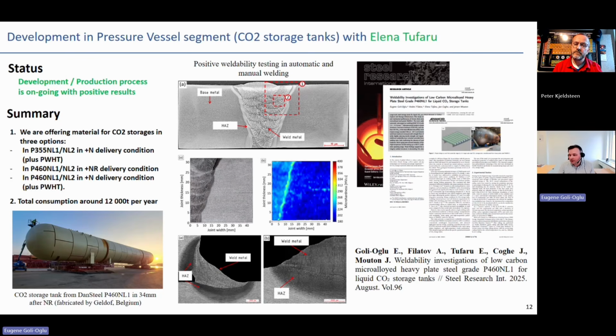Normally, this kind of material will be welded with submerged arc welding with heating input around 2 kilojoules. And then it will be split into sections. Here you see this is a base material, and this is a weld, and this is a heat affected zone. And then it will be tested in many different places. The most normal practice is to test the weld on the face side from both sides, in the middle, and also on the root side of the weld.